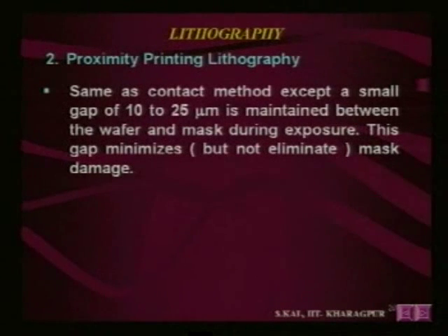Okay. Now coming to the next printing technique, that is proximity printing lithography. In case of proximity printing lithography, the optical systems are same as the contact printing lithography, but a small gap of 10 to 25 micron is maintained between the wafer and mask during exposure. That is the only difference, as I told. This gap minimizes mask damage, but you cannot ensure that it completely prevents or eliminates mask damage. Because if the dust particle is more than the gap, then surely it will damage.